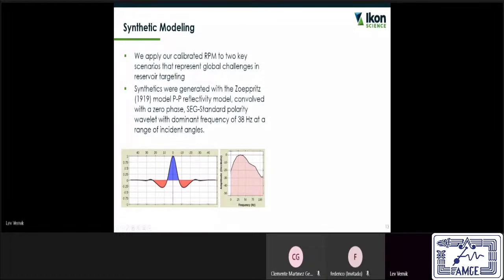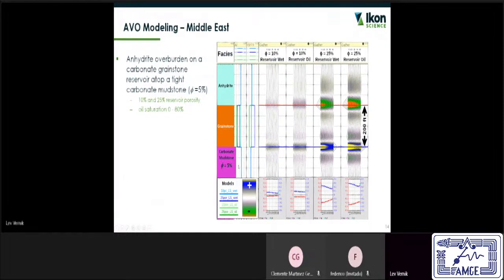So that leads us to believe that this is the model of choice, and we wanted to use that to build specific load scenarios and then explore them using Zoeppritz's equation P reflectivity, which we basically convolve with a zero phase SEG standard polarity wavelet, shown here. The spectrum of this wavelet is roughly displayed right here. And then we, by means of a blocking model, which is built using the VK model for different scenarios, like this is anhydrite, we inserted a grainstone reservoir of different porosities.